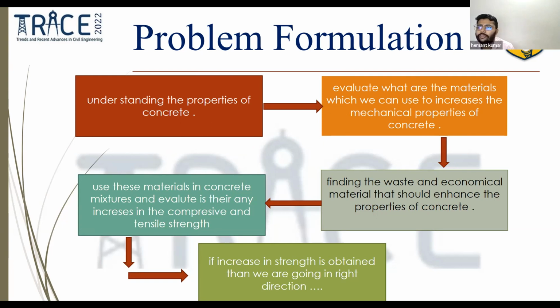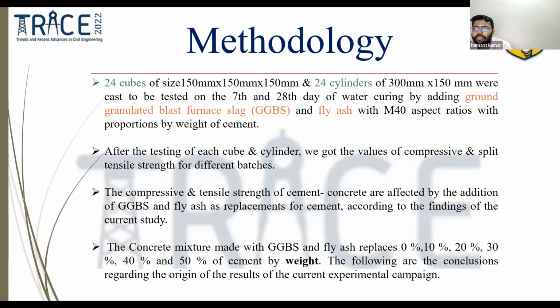Methodology. 24 cubes of size 150 mm and 24 cylinders of 300 mm by 150 mm were cast to be tested on the 7th and 28th day of water curing by adding GGBS and fly ash with M40 grade with proportion by weight. After the testing of each cube and cylinder, we got the values of compressive and split tensile strength for different batches. The compressive and tensile strength of cement concrete are affected by the addition of GGBS and fly ash as replacement of cement, according to the findings of the current study.